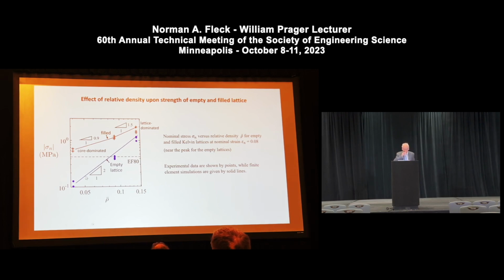And I'm plotting the strength of the empty lattice as a function of the relative density of the lattice. So you can see on a log-log scale that the lattice itself is sensitive to relative density. It's a bending type structure, and the simulation suggests a slope of 2. So down at low relative density, the lattice is much weaker than the core, and consequently, whenever you put the core into the lattice to make for this filled lattice, the overall response becomes essentially core dominated, because the core itself is much stronger than the empty lattice.